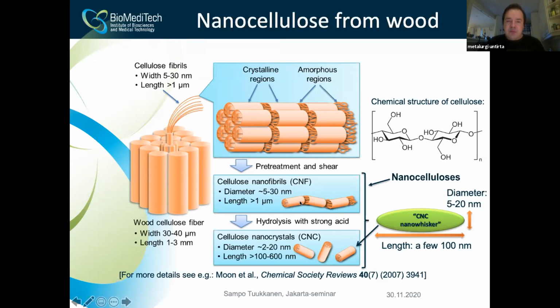If you want to go further, you can use a chemical treatment called hydrolysis with strong acids. You can get rid of the amorphous areas and end up with only the crystalline areas, which are called cellulose nanocrystals. They have a diameter of about 2 to 20 nanometers, depending on the source and the treatment, and a length of some hundreds of nanometers. They are sometimes called nanowhiskers, but nowadays people use that less, and more CNC. Cellulose nanocrystals is the more frequently used term. Okay, so this is what you can make from wood.